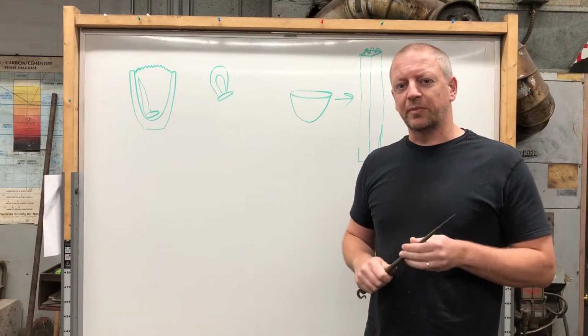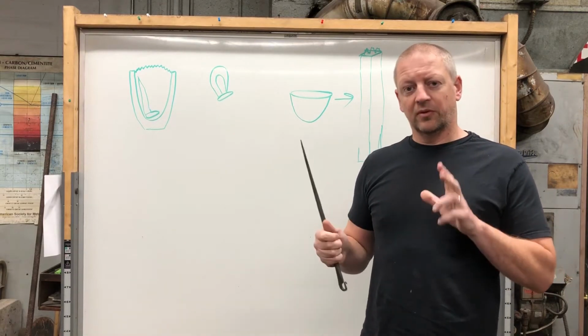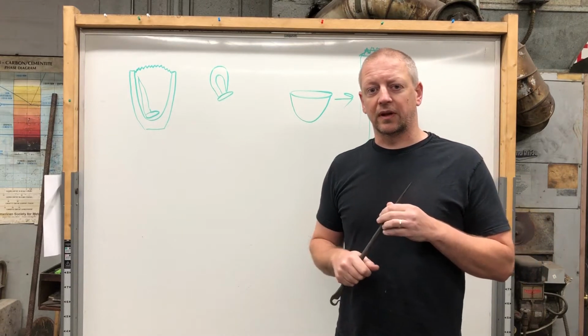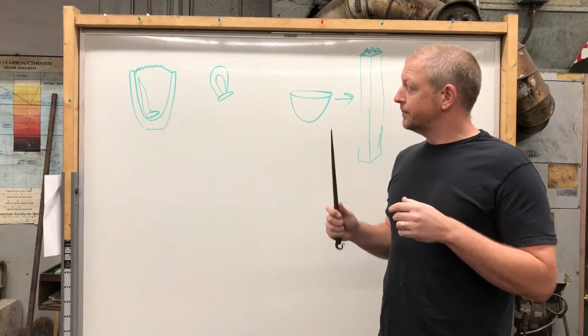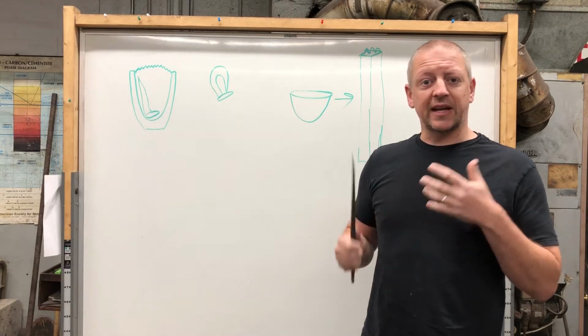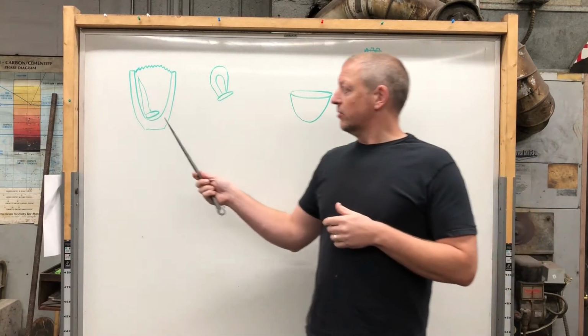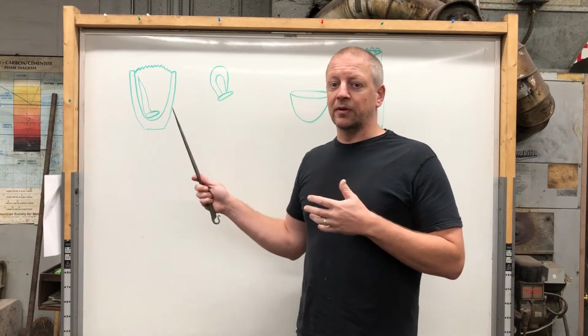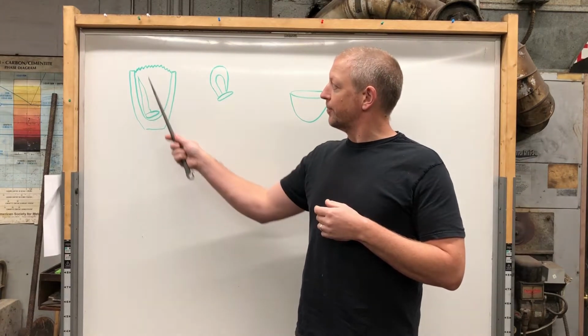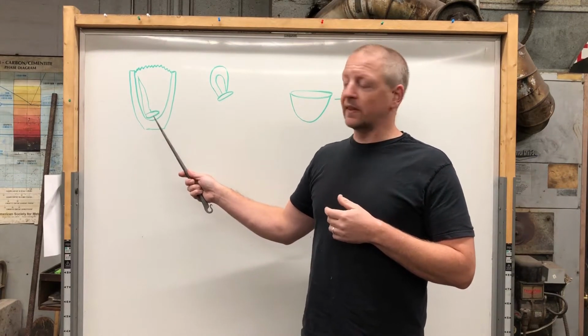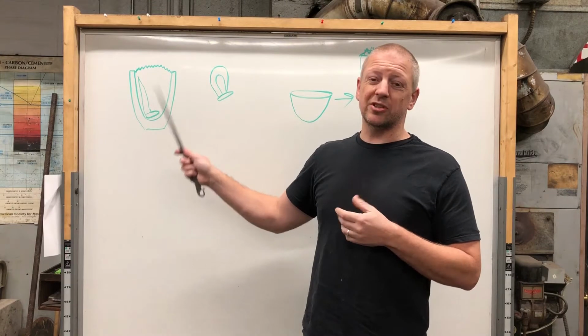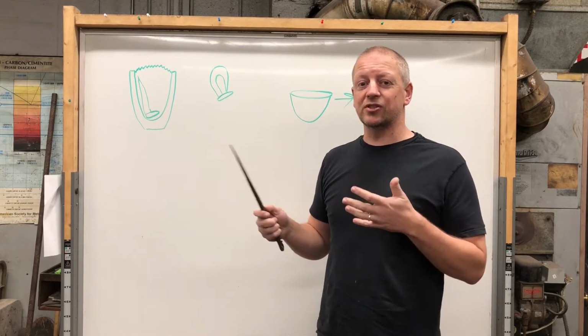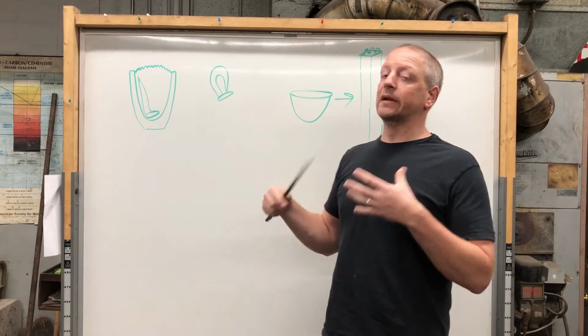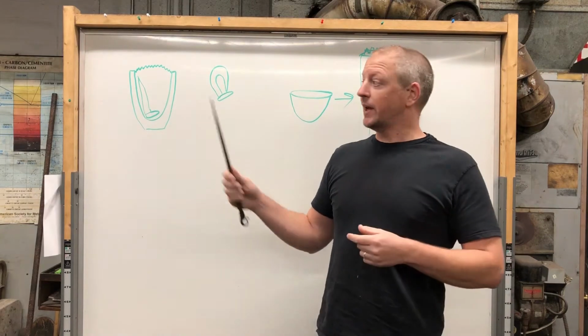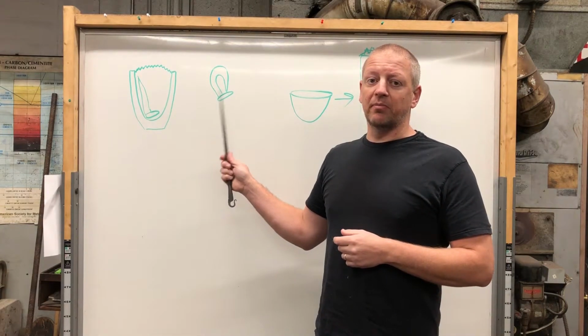So, a little bit more information about this railroad spike Wootz that I've been working on. First thing that came up as an issue was the odd shape of the railroad spikes. They were long enough that they came up close to the rim of the crucible. As soon as I saw that, I really should have paused and done something that I did later, which is just heat them up, fold them in half.